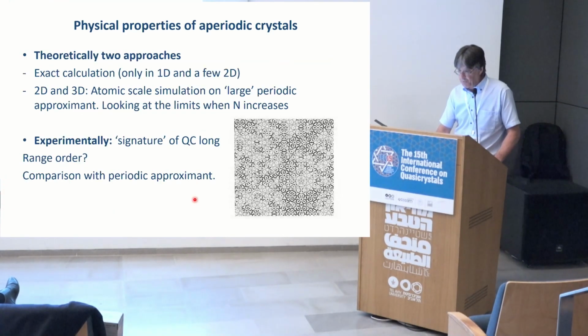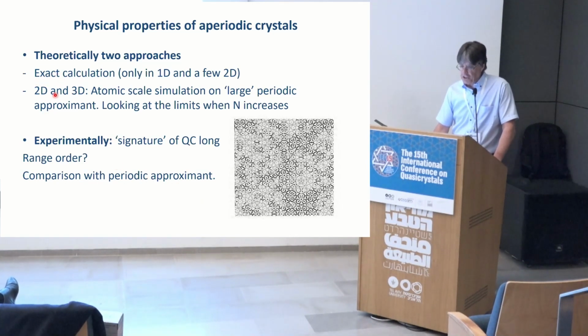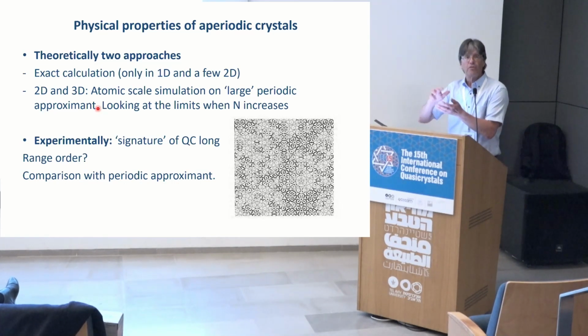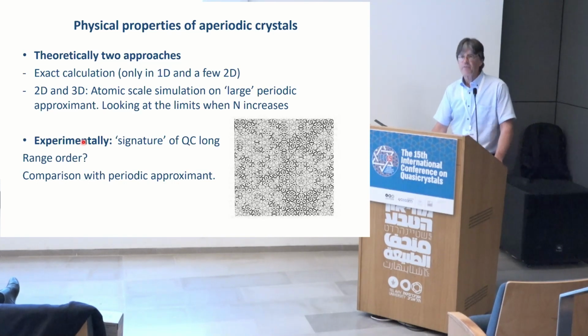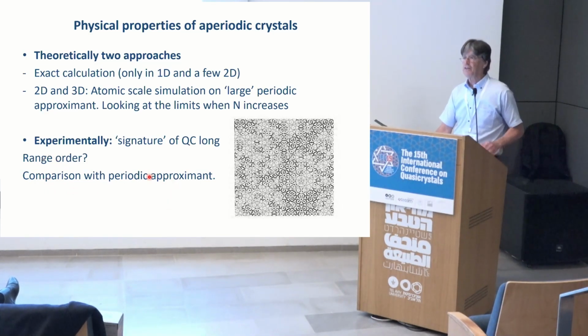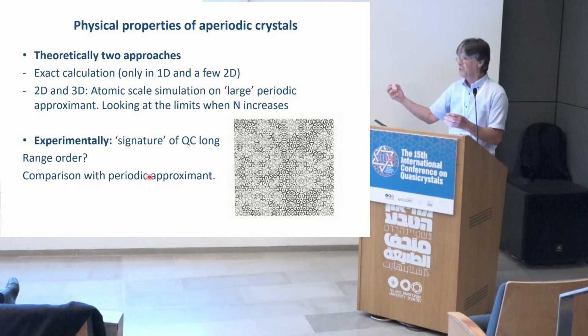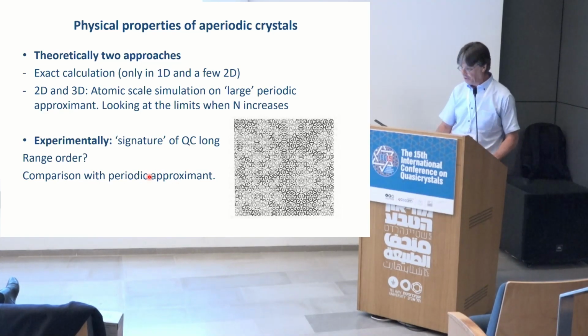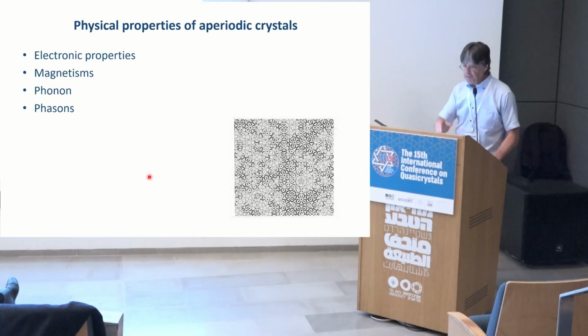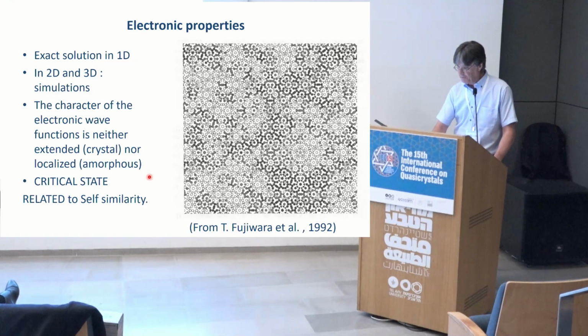And basically two approaches have been used: exact calculation, in 1D; in 2D and 3D, this is mainly atomic scale simulation on large periodic approximants, and you look at what's going on when you go further and further. Experimentally, it's even more difficult, I would say. The signature of the quasi-periodic long-range order specificity is mostly done by comparing with the periodic approximant. So if there is something special to quasicrystals, it should be different from the periodic approximant. I will briefly go through a few examples.